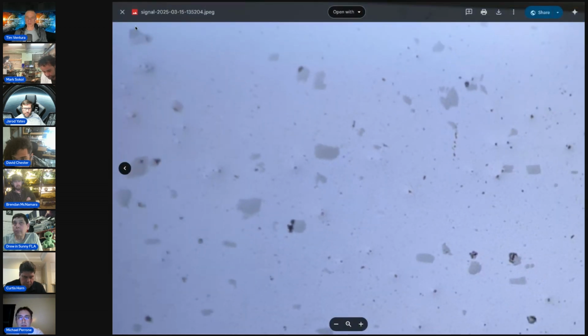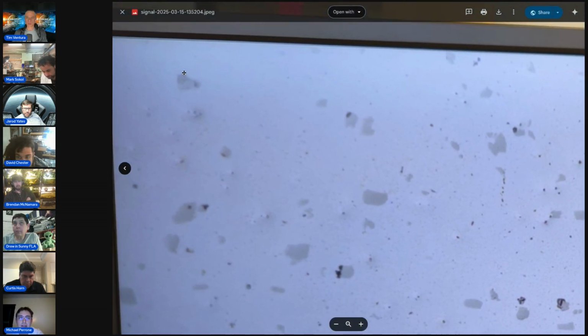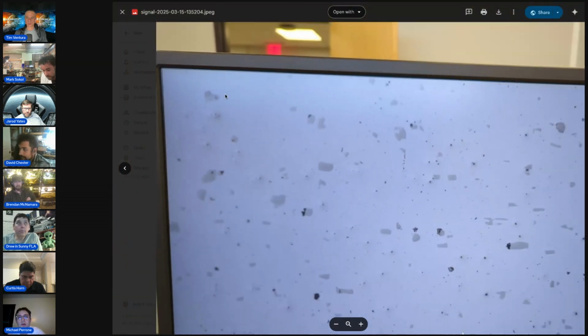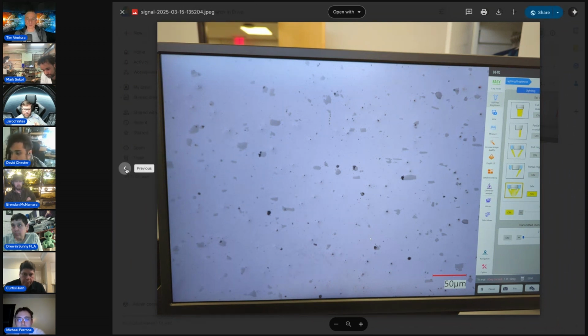There are a few areas where the material's black, but it seems like it's sort of bowed outward, which suggests that there was a hard material at that location. We'll take a closer look at that at the next opportunity. But basically the two main phases are a dark gray phase, which is aluminum and silicon, and then the lighter phase is aluminum in the optical microscopy. And then the black phase is mostly just pits, and some of it might be a hard material.